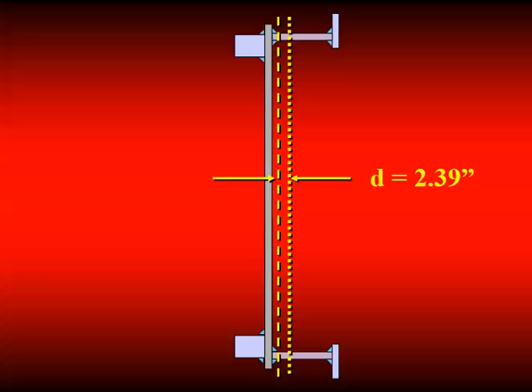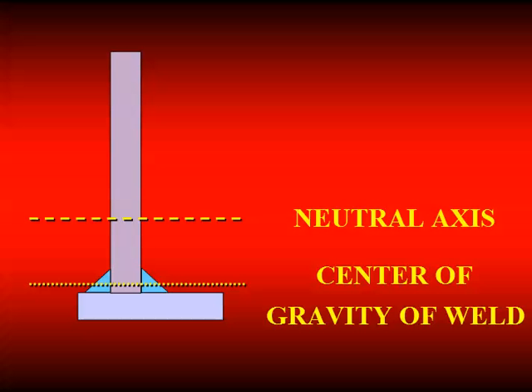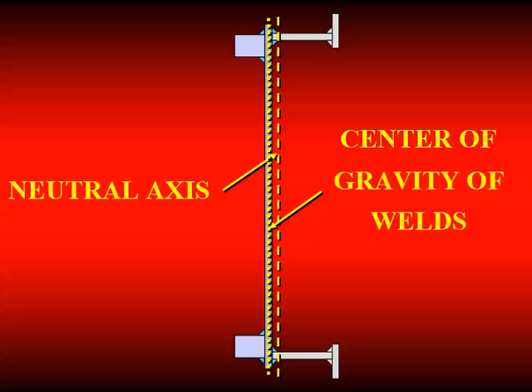So these 150-foot long members were cut into 75-foot long members and welded. Now that actually reduced the tip deflection by 75%, to a quarter of what it started with. Those were butt spliced together. They were a little bit wavy, wasn't too bad. Then those were brought in, welded onto the rest of the assembly. The neutral axis and center of gravity were close enough. They welded them up and were within tolerance of what they needed to do going forward.